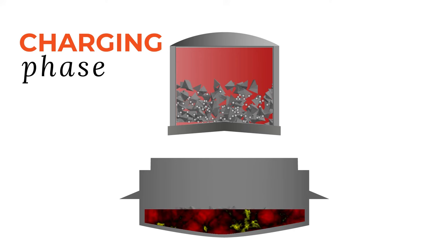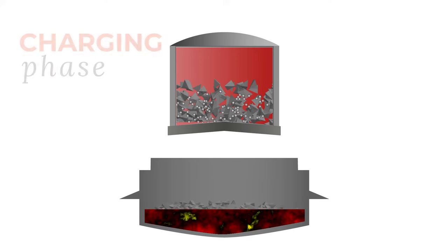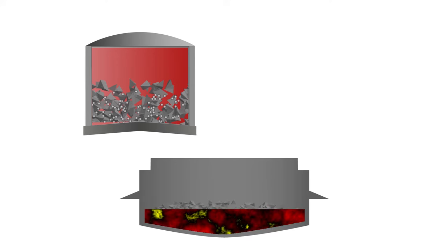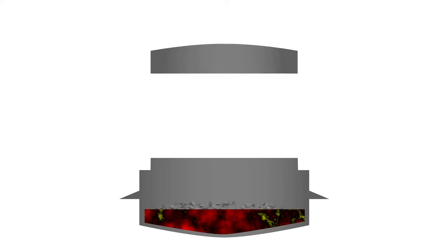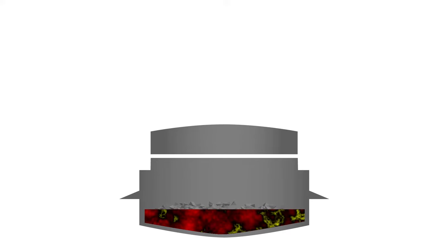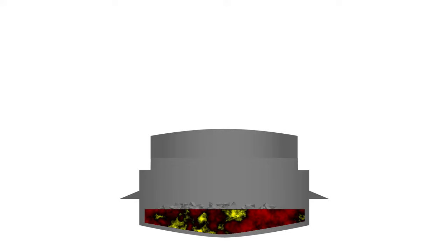A small amount of molten steel, a few tons, remains at the bottom of the furnace from the previous cycle in order to help maintain temperature and melt the charge. The furnace is partially filled with charge and the roof is replaced. The charge is then melted in stages before more charge is added.